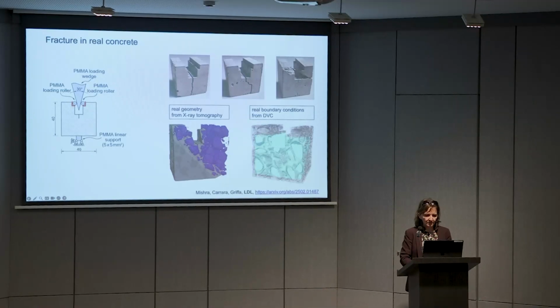We are running some true simulations, true in the sense that we are simulating the actual structure of concrete coming from an X-ray tomograph. And this is, of course, a setup, and we are using also real boundary conditions coming from digital volume correlation. And you see you have nominally identical specimens that fail in completely different ways, and we were able to reproduce these failure mechanisms by using simulations with phase field models.